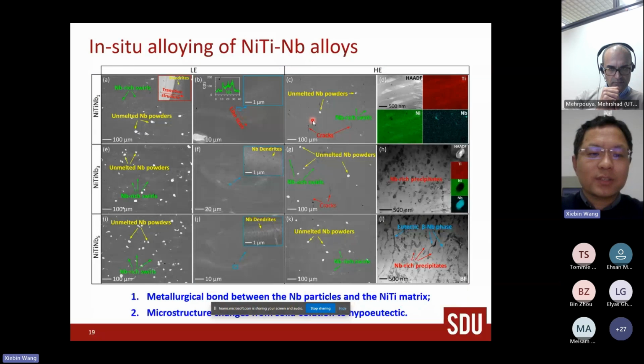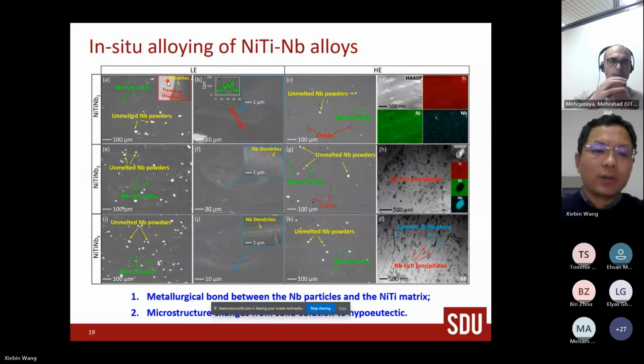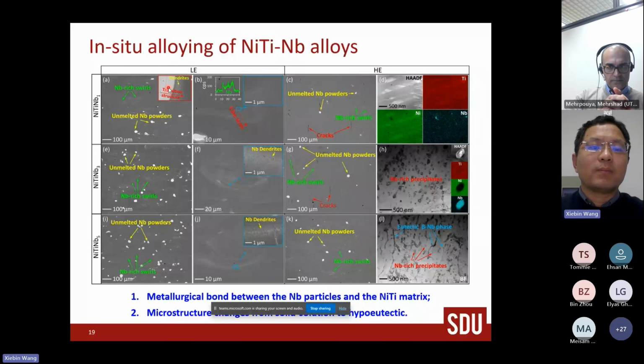And then we check the microstructure, and it's a highly inhomogeneous microstructure, and there are unmelted Nb powders, but for unmelted niobium particles, there are strong metallic bonds with the matrix, because there's a eutectic region between unmelted niobium particles and the nickel-titanium matrix. And also there are a lot of nickel-rich spherules, and in this nickel-rich region, there are niobium dendrites and cellular structures.